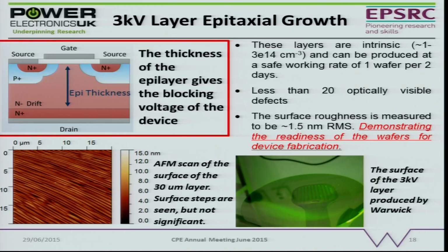So this is a picture of one of the wafers that we've grown. This had 3 kV, so a 30 micron layer on it. You can see it's transparent, which is different to silicon. And this is an AFM picture of the surface. So the surface roughness is quite acceptable.